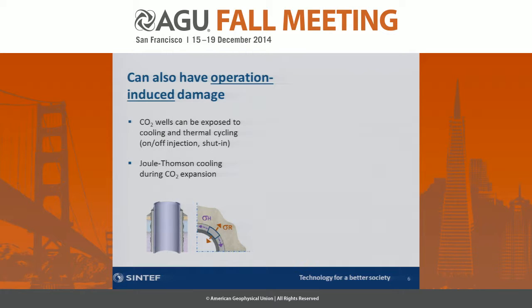And then in addition to all these defects that I've gone through now that can be present at well constructions, that are decided by which materials you use and which procedures you use for well construction, you can also have this operation-induced damage to the well. So in this case, we looked at the temperature variations in the well, because when CO2 is expanding, you have a cooling due to the Joule-Thomson effect, and that can be the case when you're injecting into a very depleted reservoir, or if you have a leak in the well.